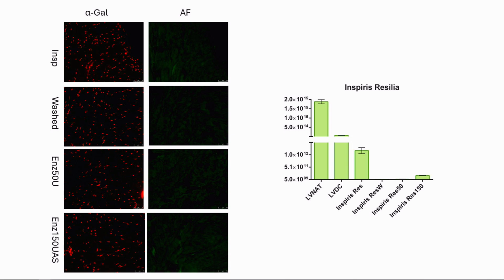One more thing is that this alpha-gal is so stubborn that even when we treat the samples, and we have also been working with animal-based or porcine fresh tissues from different cardiac samples, we found that after treatment at high temperature, ultra low temperature, or normal temperature for a very long period, it is very, very difficult to remove them, and they are not affected by physical conditions.